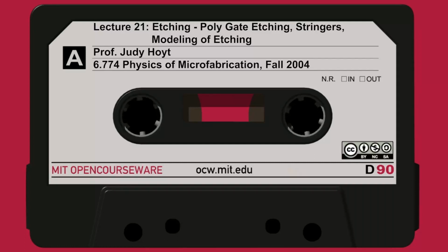Finally, we have the lowest residence time, or the lowest pressure here, at 0.1 millitorr. This paper demonstrates very vertical sidewalls and no undercutting. So this would be considered a very good quality etch. You may be able to make one device with this etch. I'm not saying this etch won't work, but from a manufacturing point of view, how do I control my line width or my critical dimension? It's not well controlled at all. So this would not be considered a manufacturable type of process.